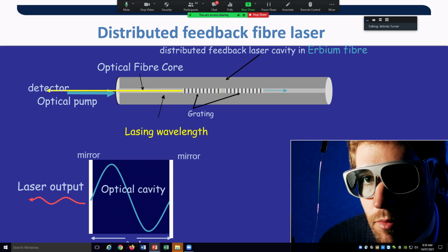Because this is ANFF, I'm going to explain briefly how these devices are made, or we're going to have a crack at it. First you need to start off with silica optical fibre that's been doped with germanium to make it photosensitive, and with erbium, a rare earth, in order to activate it.